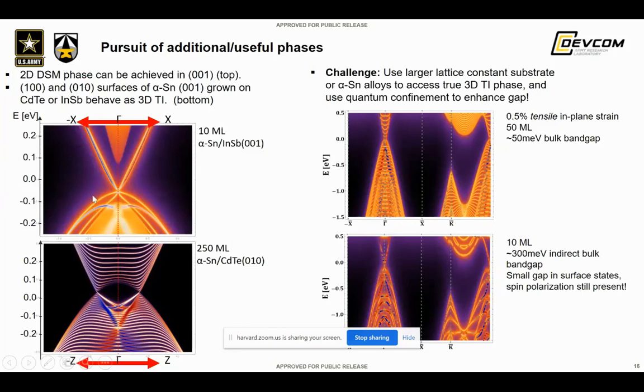as shown by these ARPES simulation plots. So the interesting thing is that the Dirac semi-metal, if you project to different surfaces, has different behavior, and whether you can see the ARPES clearly or not, or 3D TI behavior. So it's somewhat dependent upon the direction of the surface state that you're looking at, depending upon the material grown. So that's interesting, but this is experimentally very difficult to realize, that is, doing ARPES in a 1-0-0 direction if the material is grown in a 0-0-1 orientation typically.